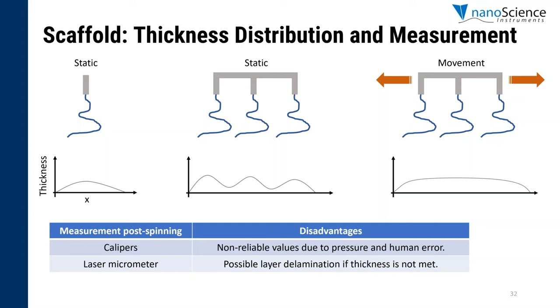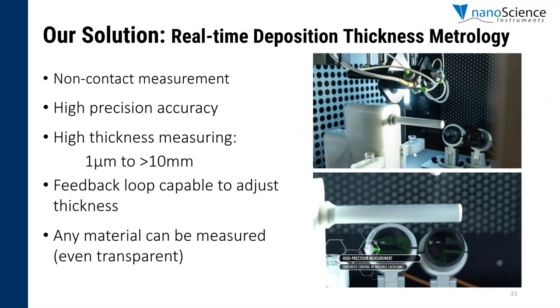So what researchers usually do to measure the sample thickness is use calipers. This is not reliable, as applying too much pressure will give you a false thickness. An alternative is creating a sample and using a laser micrometer, but then if you don't obtain the right thickness, what people usually do is take the same sample, put it back in the spinning process, and measure it again a second time. Let's say that you get the right thickness, but then you might have delamination. That's one of the issues. So ideally, we should have a better way to process and make sure that we can measure sample thickness.